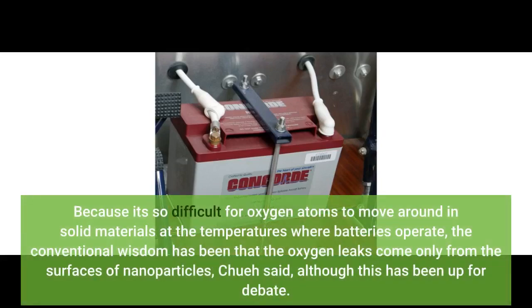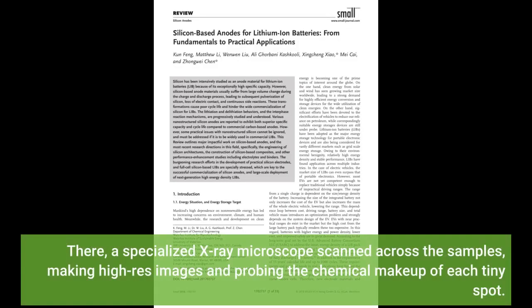Because it's so difficult for oxygen atoms to move around in solid materials at the temperatures where batteries operate, the conventional wisdom has been that the oxygen leaks come only from the surfaces of nanoparticles, Chueh said, although this has been up for debate. To get a closer look at what's happening, the research team cycled batteries for different amounts of time, took them apart, and sliced the electrode nanoparticles for detailed examination at Lawrence Berkeley National Laboratory's Advanced Light Source. There, a specialized X-ray microscope scanned across the samples, making high-res images and probing the chemical makeup of each tiny spot.